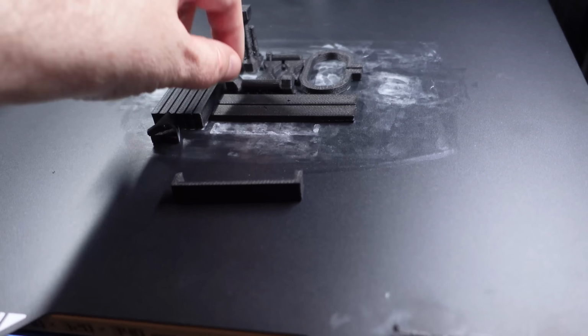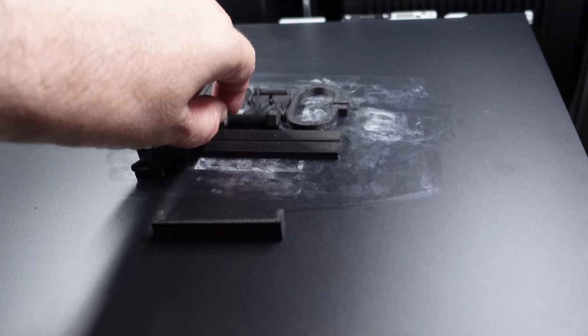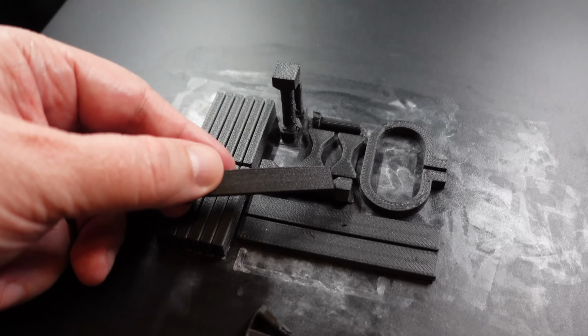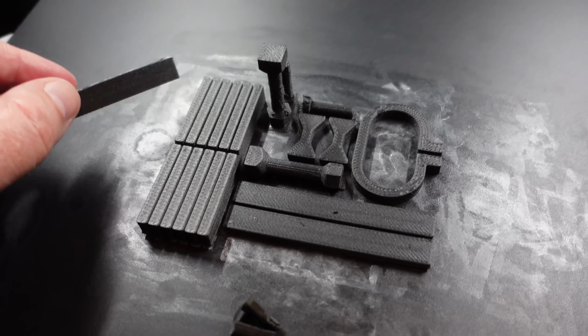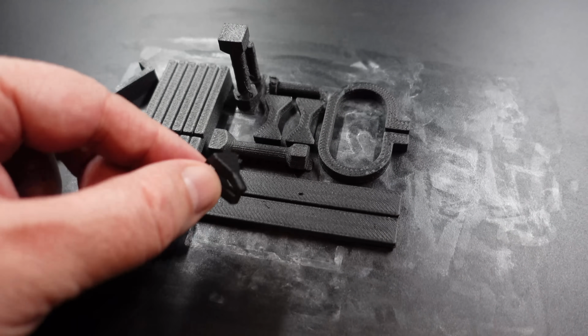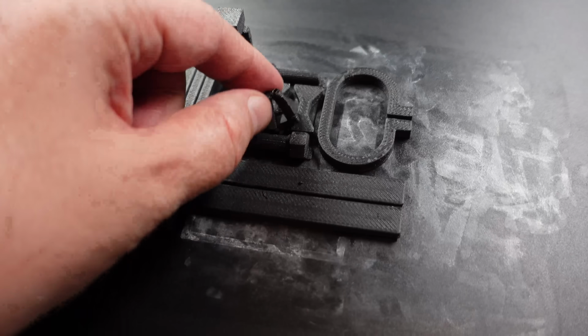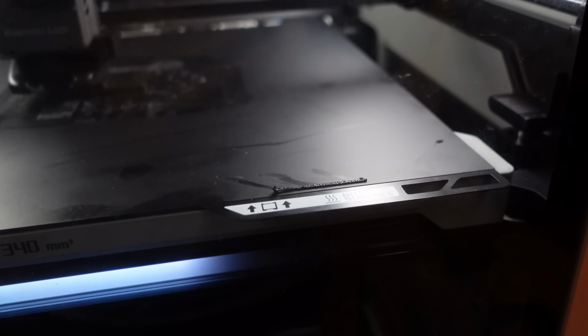Yes, the adhesion is good, so warping is the problem. Actually, the print quality is acceptable. Probably brim will solve the problem, but only this test object I have to reprint. For this reprint I'm using a smooth PEI sheet, and from this purge line it looks like the bed adhesion is better, but I don't want to open it until it's finished.